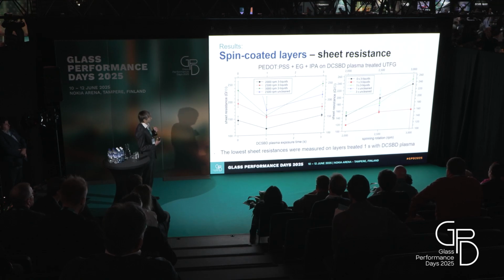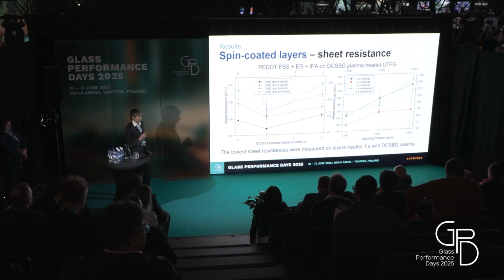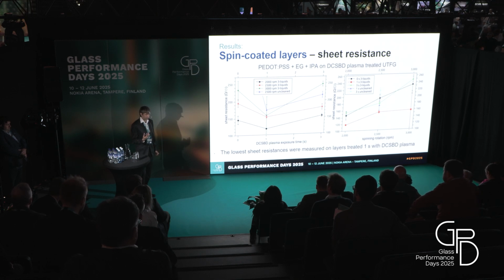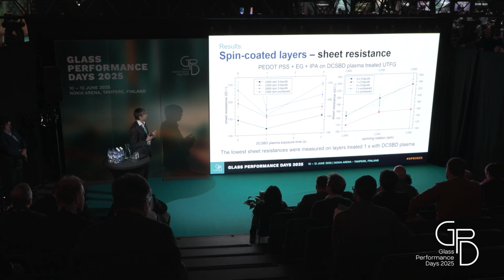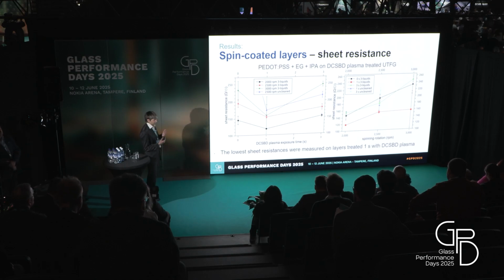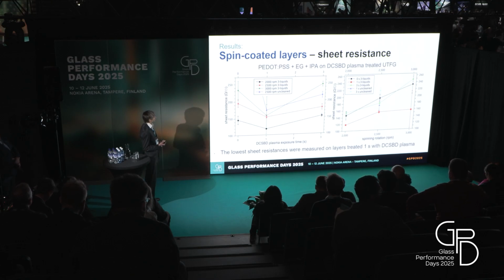And first, the coatings on the spin coater are rotated at the same rotations, for the same time, and the drop is the same. So the sheet resistance was consistent enough to see the effect of plasma. So these are the graphs of sheet resistance. We expect that the thickness is similar in these coatings, and we measured it, it was around 80 nanometers.